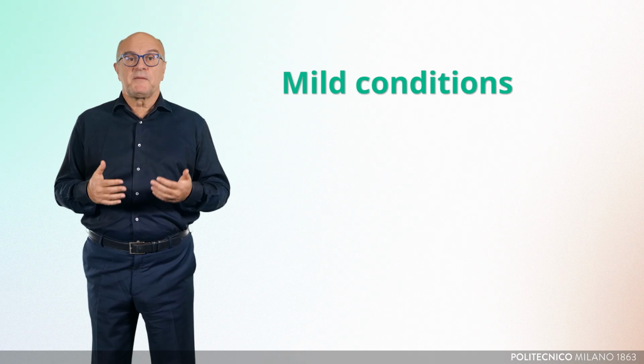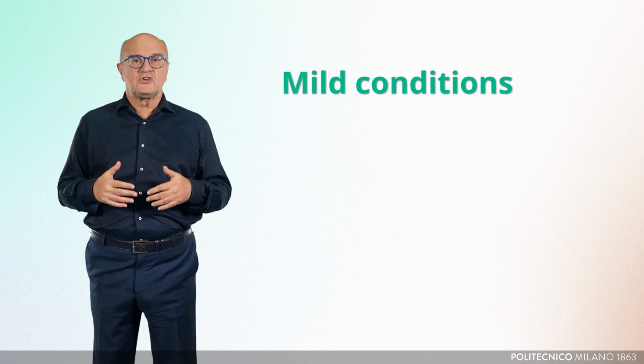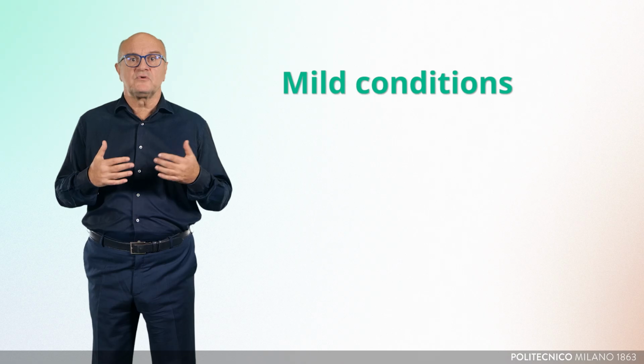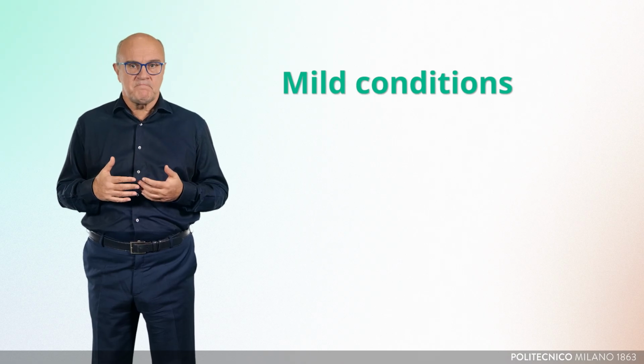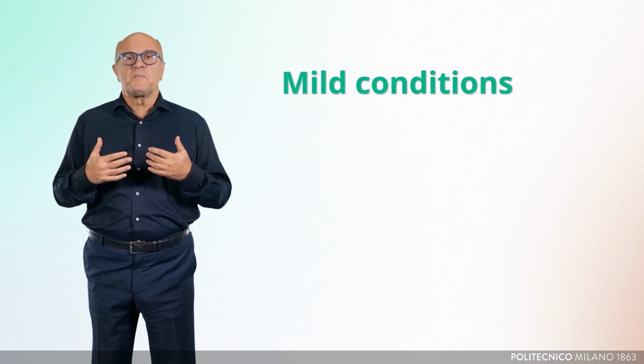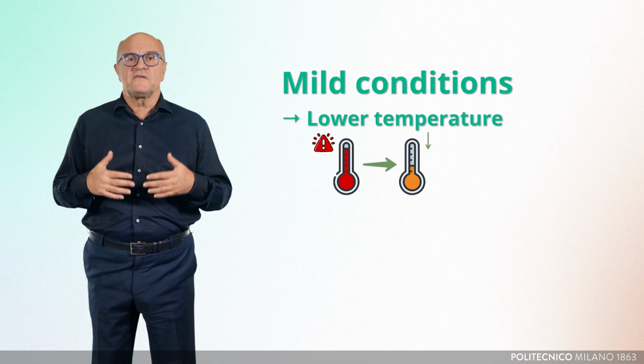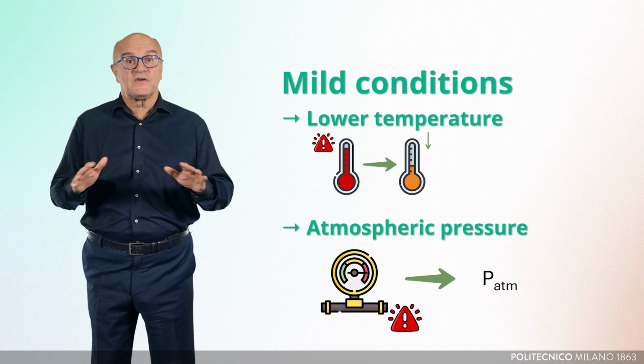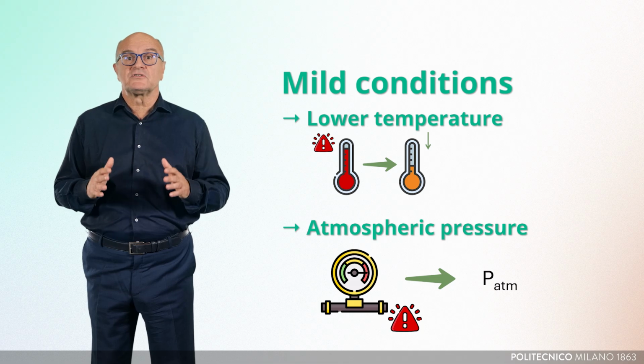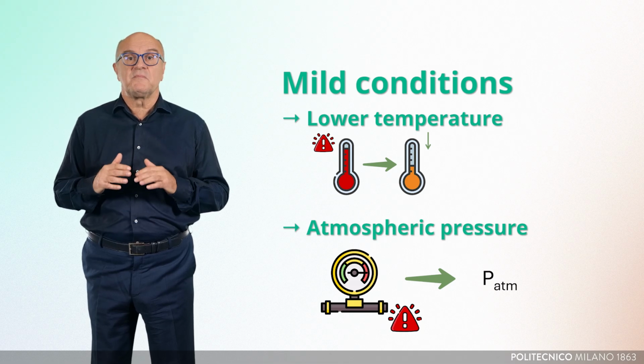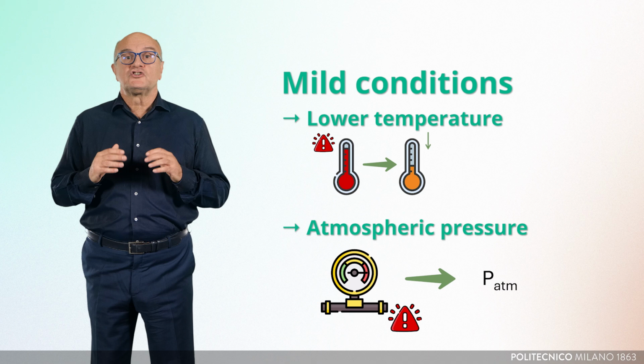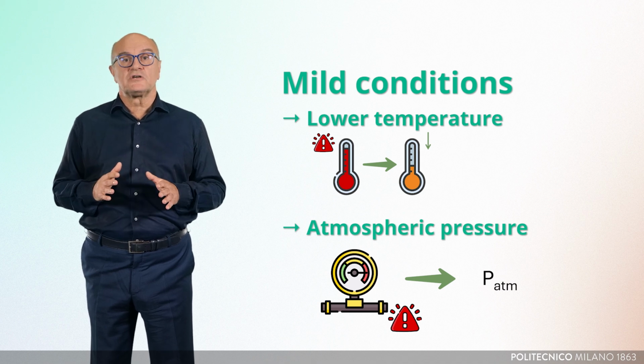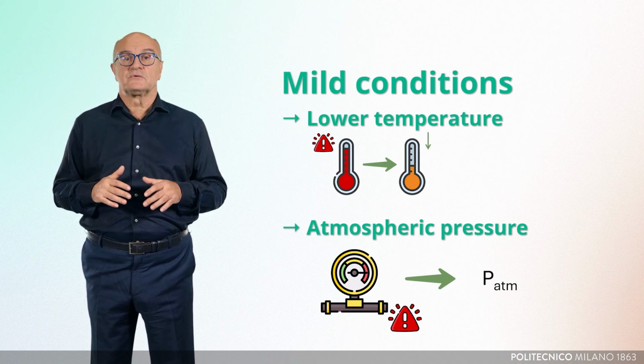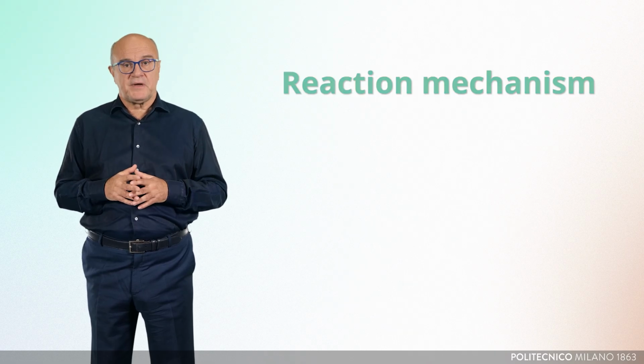Second point, mild conditions. Unlike pyrolysis or gasification, which require very high temperatures, up to 300 to 800 degrees C, solvolysis may operate at temperatures around 150 to 200 degrees C and atmospheric pressure, making the process energy efficient and environmentally friendly. The choice of the right catalyst is crucial in order to reduce the temperature and time needed for the process. Third point, the reaction mechanism.